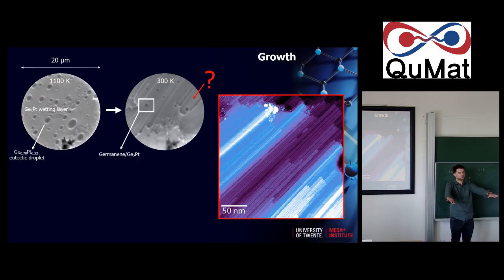So you have a more spread out platinum on top of the surface. And we saw that if you do that and you cool down, then germanium likes to segregate on top of the surface. So what we have here is that result. It's germanium from the bottom that segregates on top of the spread out platinum layer that remains on the surface. And these have these elongated structures because the crystal that we use is a 110 cut germanium, and that has an anisotropic structure. So that follows the same crystal orientation as the substrate.